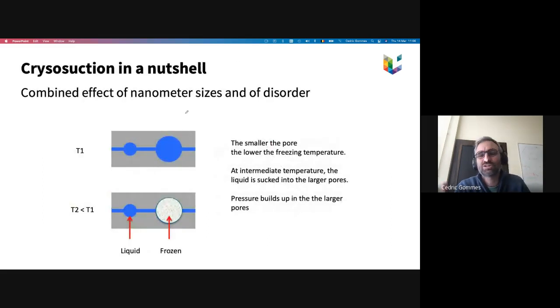I'm going to explain this here just as an illustration of things that I'm interested in. This particular effect results from the combined effect of nanometer-sized pores and disordered structures. The story is that the freezing temperature of liquids in pores depends on the pore size. Basically, the smaller the pores, the lower the freezing temperature. So if you cool this benzene in cement progressively, you reach a point where you start to freeze benzene in the larger mesopores, but it remains liquid in the smaller pores. As a consequence of benzene being frozen in larger pores, the chemical potential drops in these pores, and so the liquid from the other pores is being sucked into these larger pores.